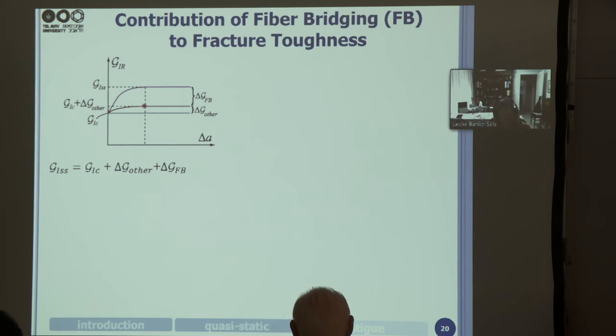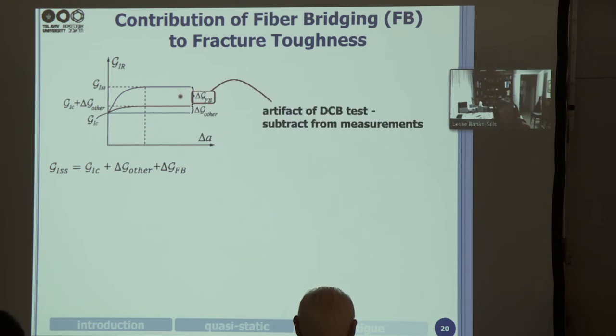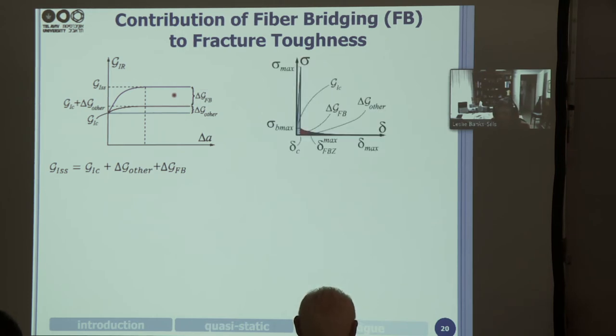And now we're coming to our aim. Our aim is to evaluate the contribution of the fiber bridging to our G1R curve. G1SS is composed of, first of all, G1C, and then what's called delta G other, the other dissipative mechanisms, such as matrix cracking and so on, and we have delta fiber bridging. What we want to do is evaluate delta fiber bridging and eliminate it. The red curve is the G1R curve that our structure is going to feel because it doesn't have fiber bridging in it. The fiber bridging is an artifact of the DCB test, and we want to subtract it. So we have to evaluate it.